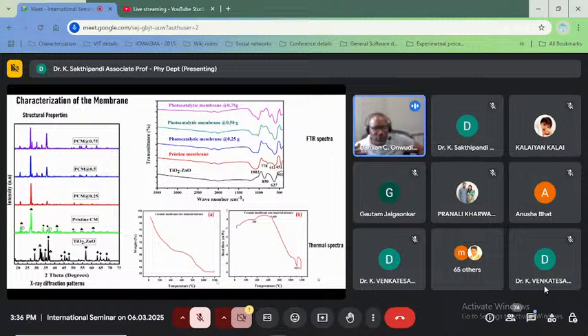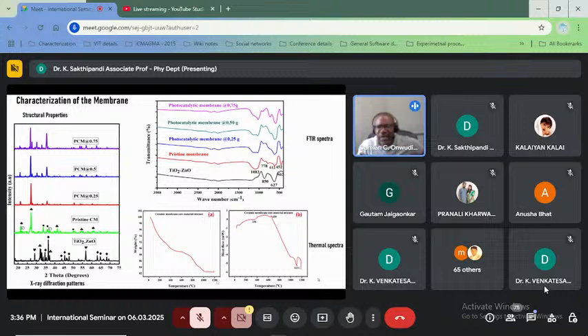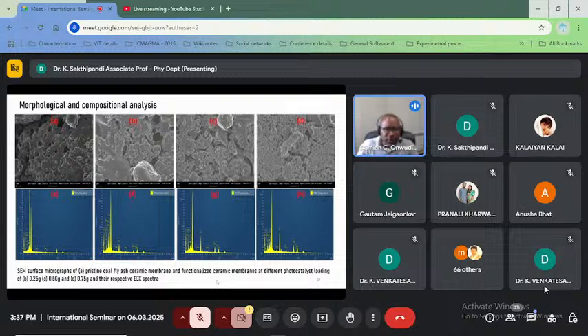So we did XRD to establish that we have actually functionalized the ceramic membrane with nanomaterial, and that is what XRD was able to establish. We then did FTIR to look at the functional groups present on the surface of the material, and to establish the effect of the nanoparticles on the surface chemistry of the ceramic membrane. As well, we did thermal TGA to look at the thermal strength of the material. We found out that as we increased the amount of nanoparticle, the thermal stability of the ceramic membrane also increased. Next slide, please.